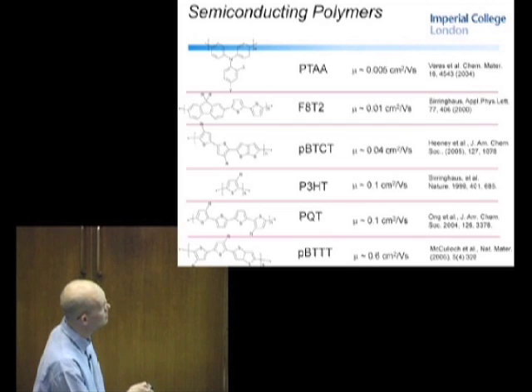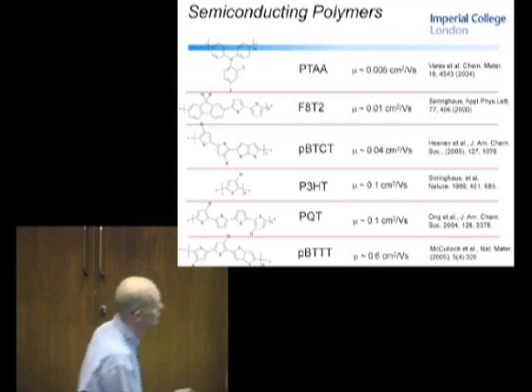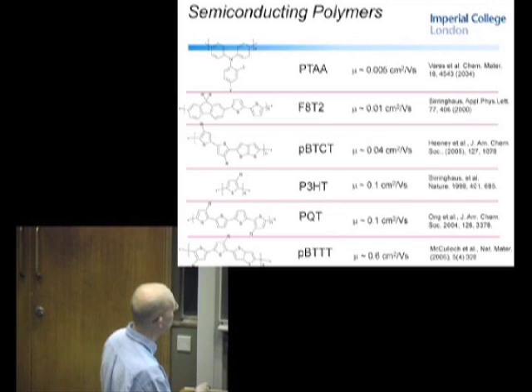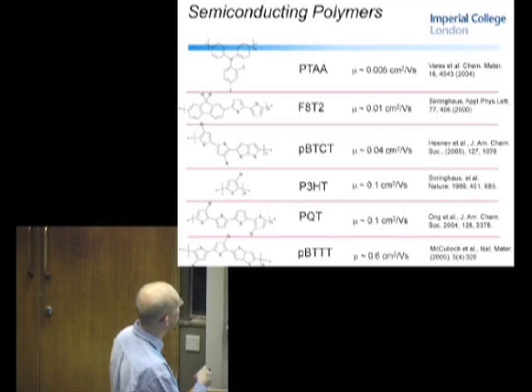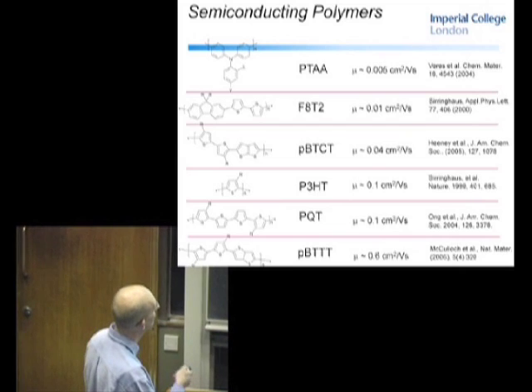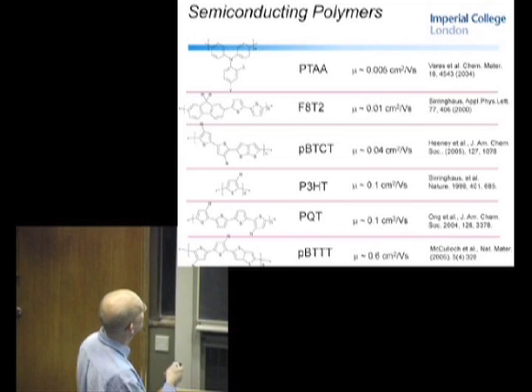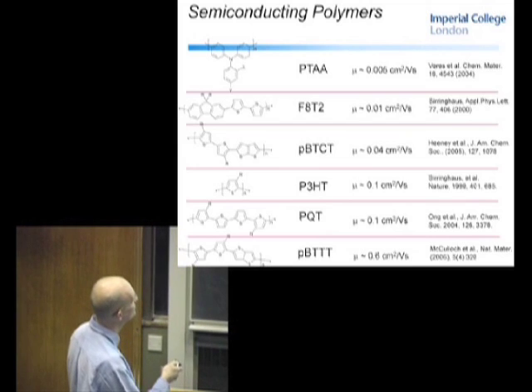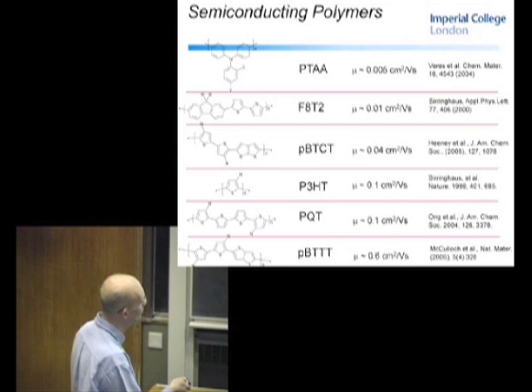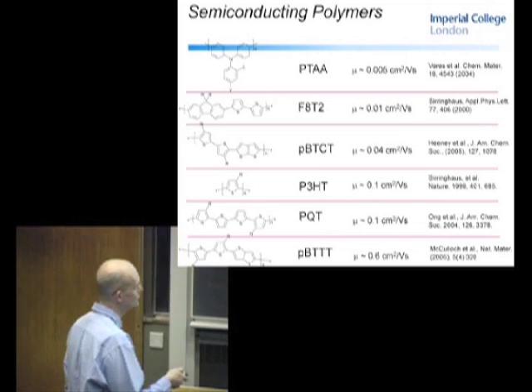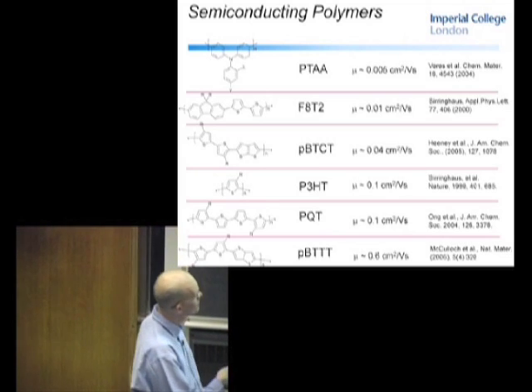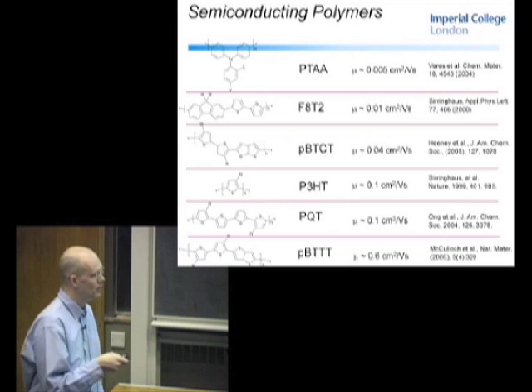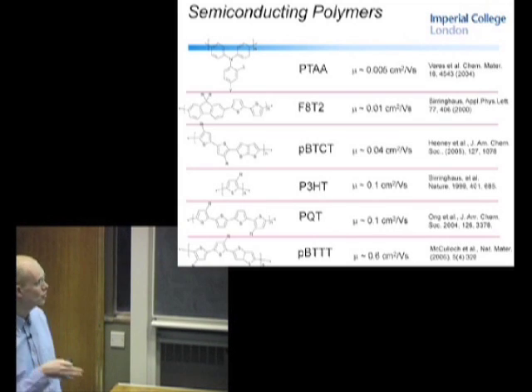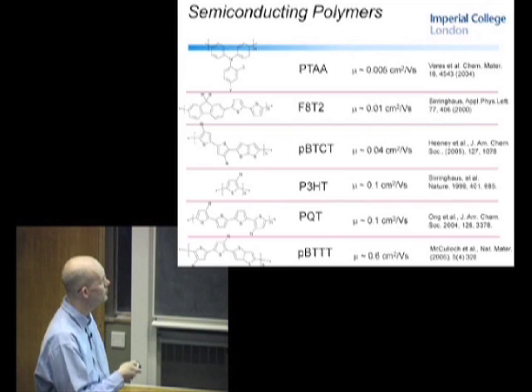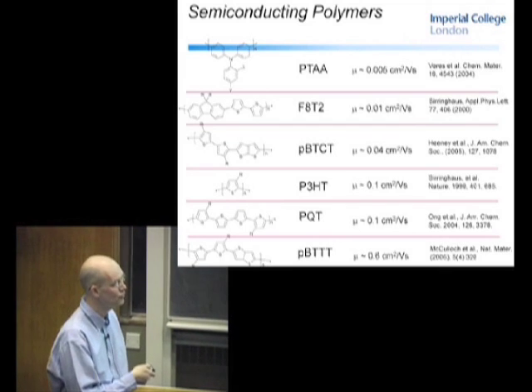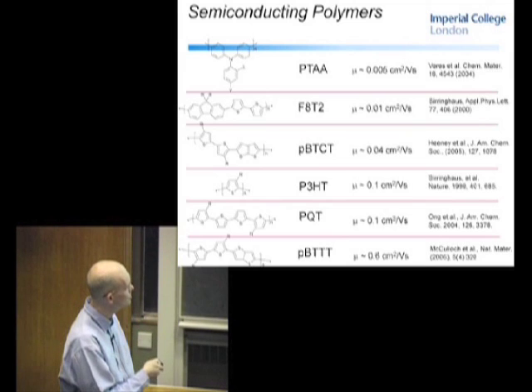If anybody's interested, there's a list of citations here. This is one that we've been working on here at Merck. We've also worked on regioregular polyalkylthiophenes and other thienothiophene polymers and arylamines and other classes of materials. Mobilities have been able to reach above 0.5, and the latest results from the NIST group with this material here, using a high work function metal to reduce contact resistance, I think it was platinum, they were able to get charge carrier mobilities of over 1 with this particular material, which is PBTTT.